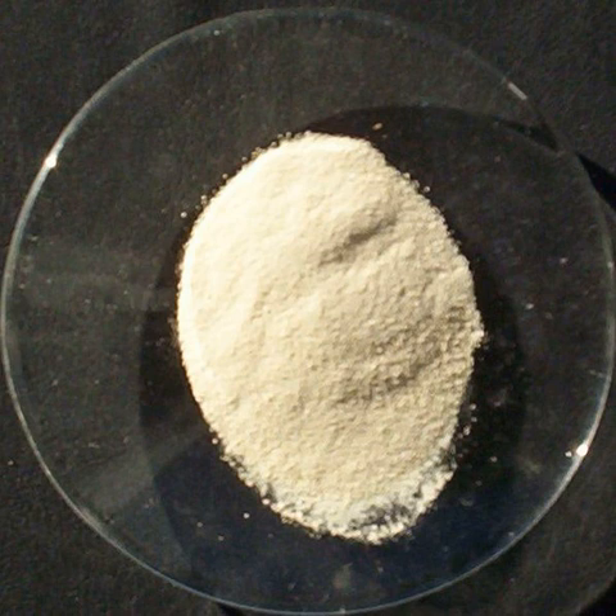This material has the formula CeO2-x. The relation x/0.35 = (106,000 Pa / pO2)^0.217 exp(-195.6 kJ/mol / RT) has been shown to predict the equilibrium non-stoichiometry x over a wide range of oxygen partial pressures, 10^3 to 10^-4 pascals, and temperatures of 1000 to 1900 degrees Celsius.